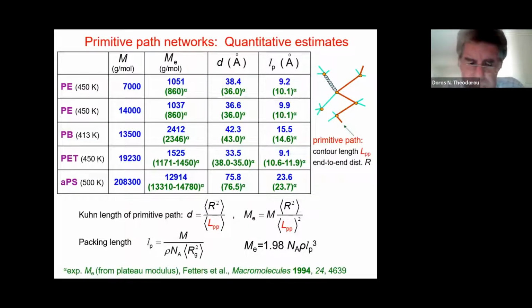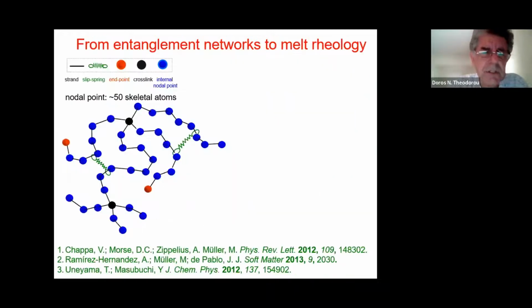And what we see is that the simulation estimates obey an empirical relation that has been proposed for estimating molecular weight between entanglements based on the density and the packing length. And that is obvious because both the packing length and the entanglement properties are predicted in very good agreement with experiment. Now, can we say something about the rheology of these melts, which is of interest in polymer processing?